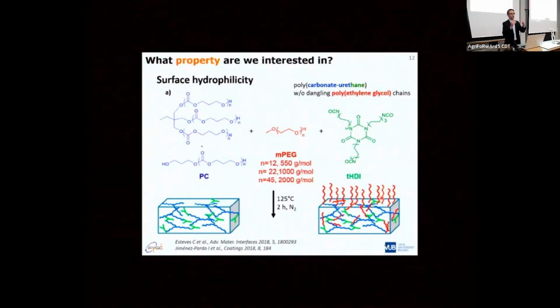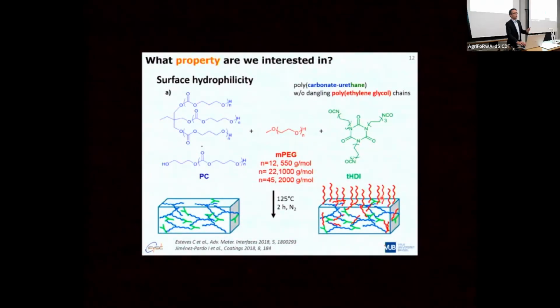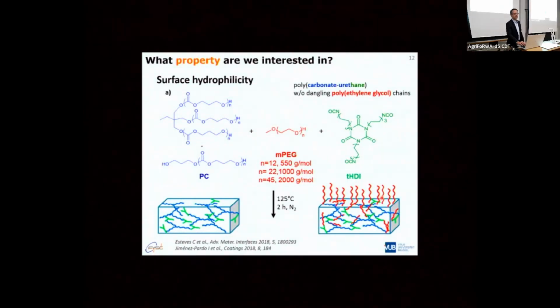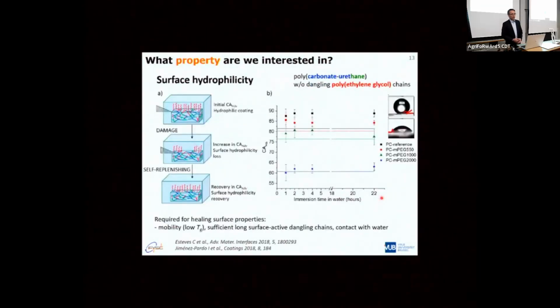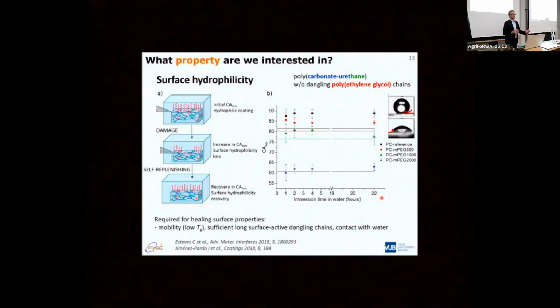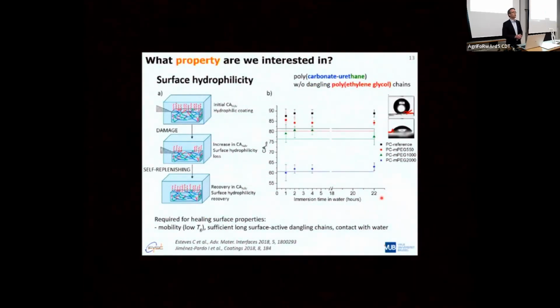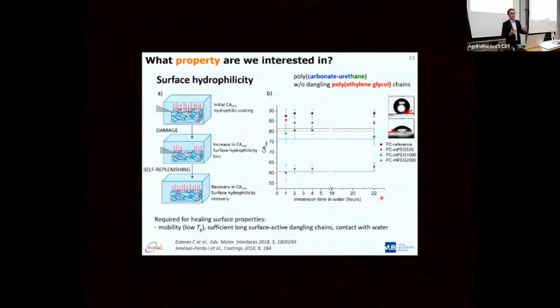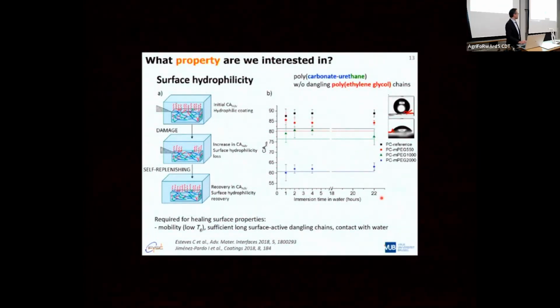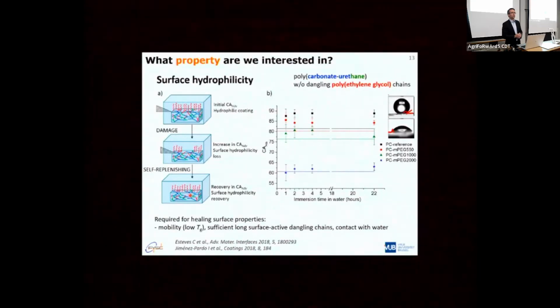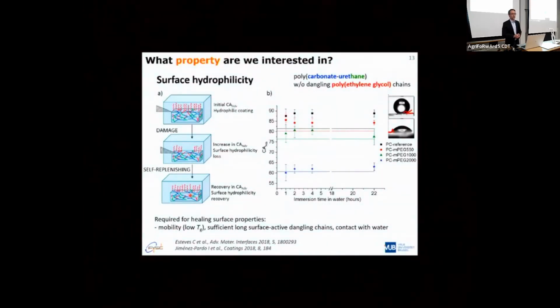The ones close to the surface will migrate to it and will make it hydrophilic. But of course, if that surface layer is removed, you want to make sure that it's replenished again, that new chains will come there, that you didn't just remove the dangling chains and hydrophobicity is there again. So they designed the material, they made sure that the properties, the length of the chains, the number of the chains were such that you have this surface replenishment, and that whenever a surface layer is removed, new hydrophilic chains come up to the surface, and that you retain that hydrophilic behavior that you were aiming for.